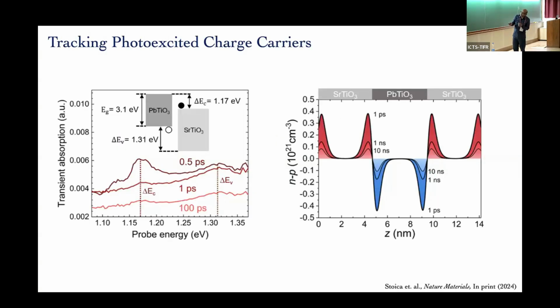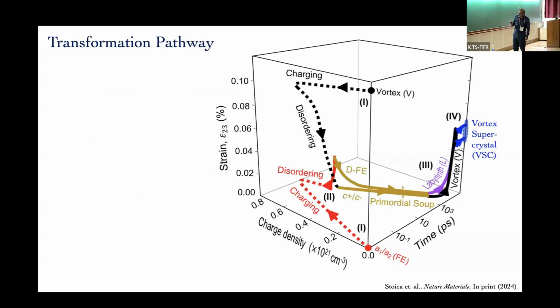we know where the charges went because when you pump the charges, this is transient absorption spectroscopy, where we know that the electrons jumped from lead titanate to strontium titanate and holes from strontium titanate to lead titanate. And right at the interface, the charges are separated, they form these dipoles. And they are very, very important in stabilizing that soup. Okay? So I'll have to let you read that.